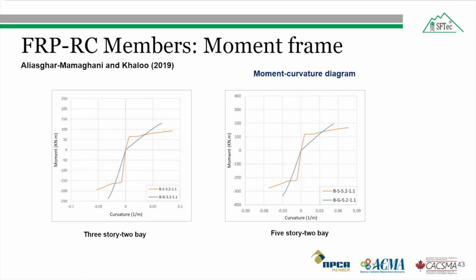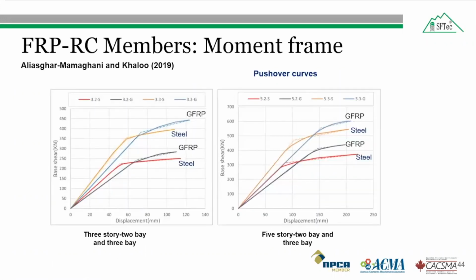So therefore, considerable moment capacity of the GFRP reinforced section can be achieved even with a low reinforcement ratio for resisting the positive moment. As seen in the pushover curves, the moment frames reinforced with GFRP bars show high load carrying capacity because the GFRP bars possess higher tensile strength than the steel bar.